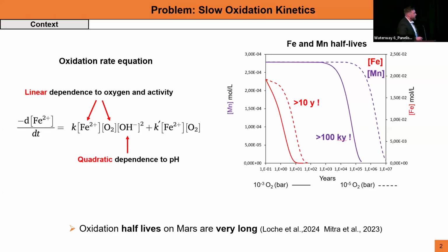So even if we don't have a lot of oxygen, or even if we have a little bit, the limiting factor is going to be especially the pH, which translates into very long oxidation half-lives of manganese and iron on Mars. For example, here, more than 10 years for iron might not mean that much for the Mars community, right?